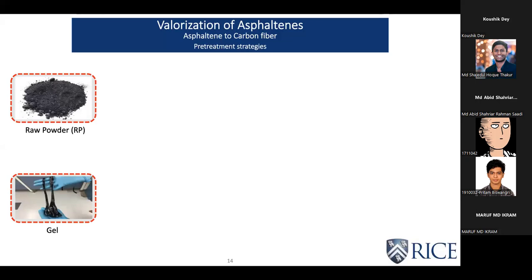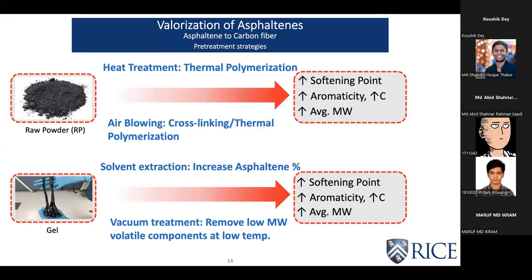And if you remember, I discussed at some point that the pretreatment strategies are very important for any type of carbon fiber production. So our first goal was to develop the pretreatment strategies. We tried different types of pretreatment routes for both of the samples. For raw powders, we tried heat treatments, which would generate polymerization, and air blowing, basically heat treatment in the presence of air flow. And for gel samples, we tried solvent extraction and vacuum treatment.